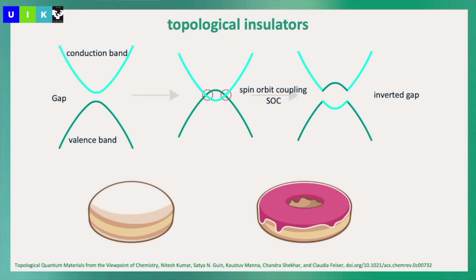So you have this forbidden crossing, and depending on the symmetry, at this time we were mainly looking at the symmetry of the bands, but now we are looking at the topology of the bands. So is this crossing allowed? Can they cross here? Or do we open up a band gap in the band structure? And this is the case if we have heavy element compounds and certain symmetry. So we have spin-orbit coupling, and then we open up a band gap and we get a topologically distinguished semiconductor from the normal trivial one like silicon. So we have this with the inverted band structure, and this leads to this topological surface state.